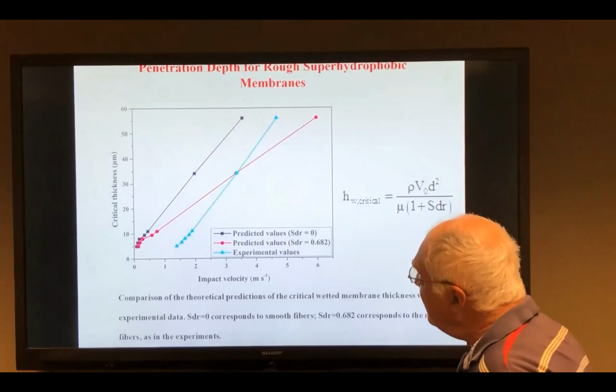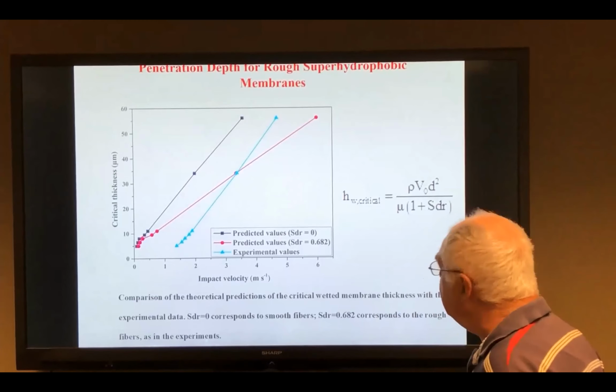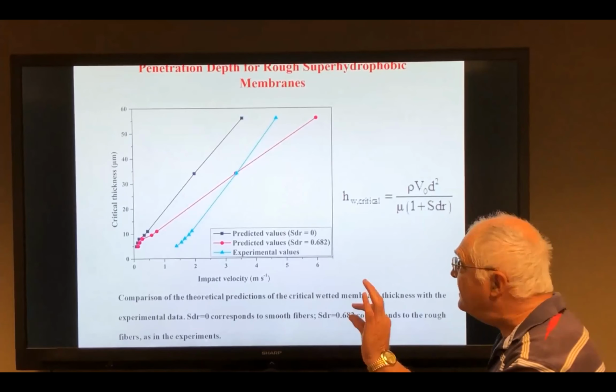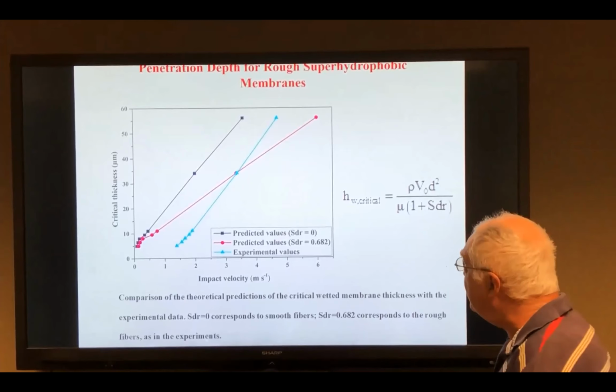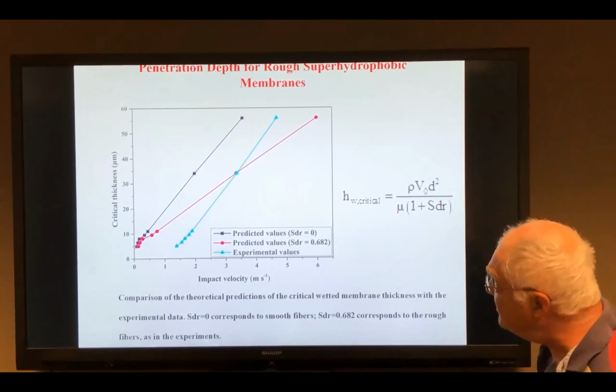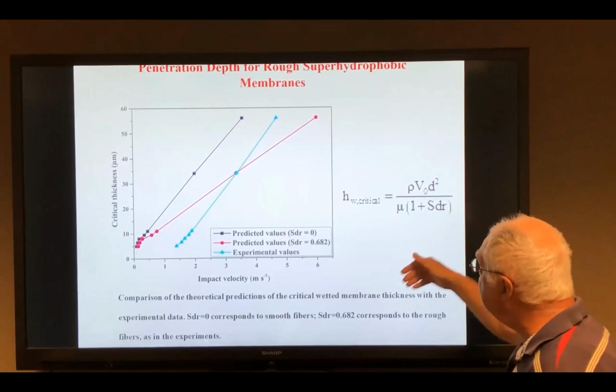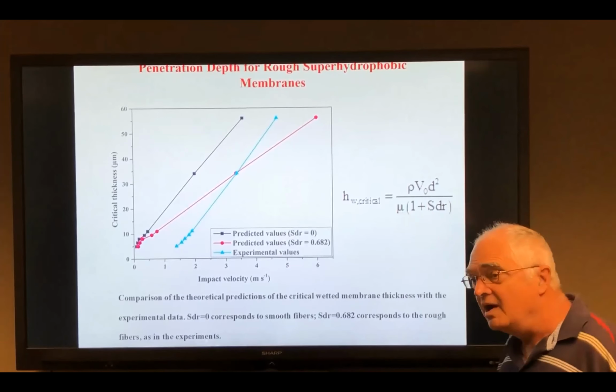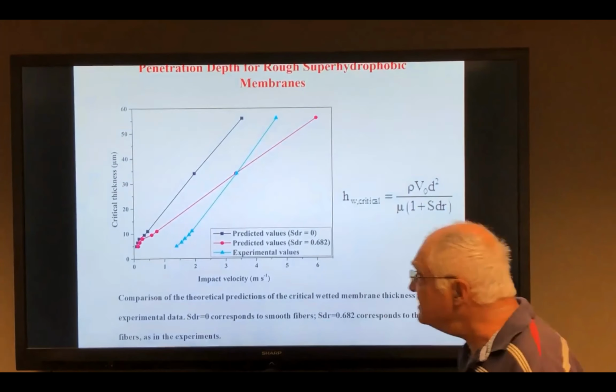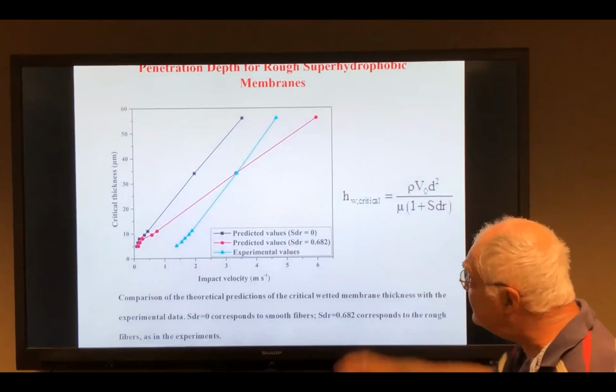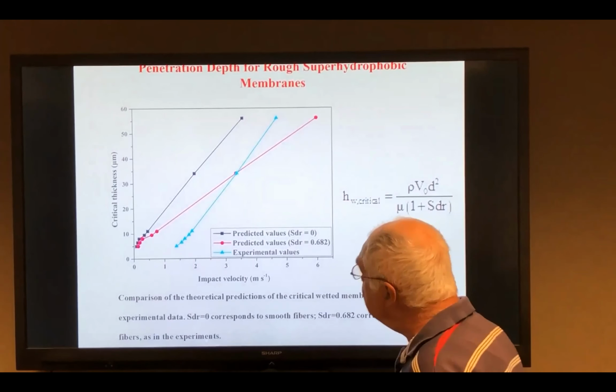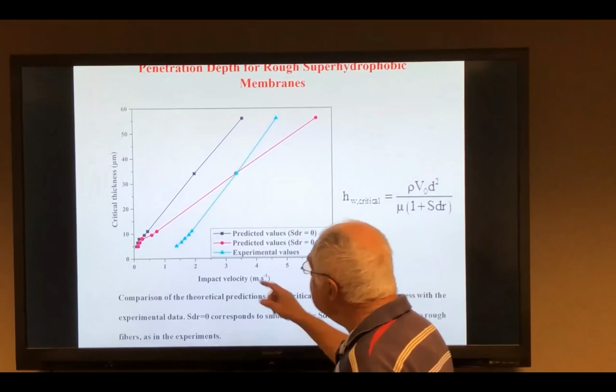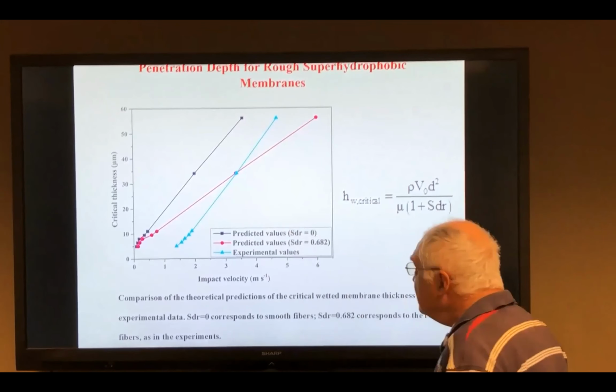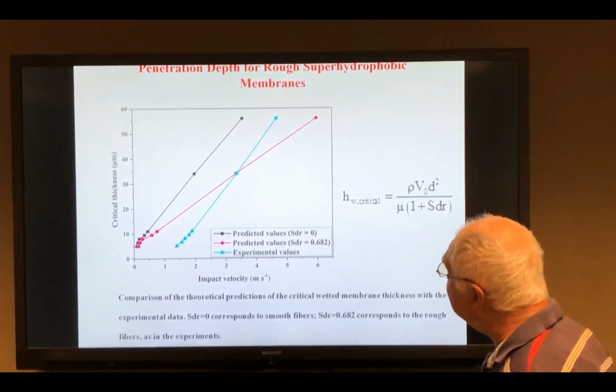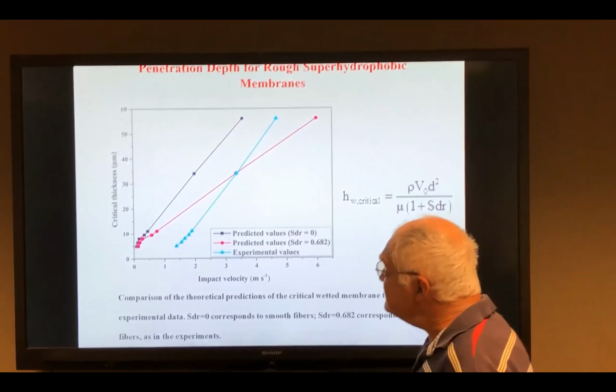I told you that the membrane should be thicker and thicker to stop penetration, and we developed a theory which accounts for the viscous dissipation inside the pores. That's a prediction compared to the experimental results. This is a prediction, this is the experimental results. At least they are in the same range. This is a critical thickness.